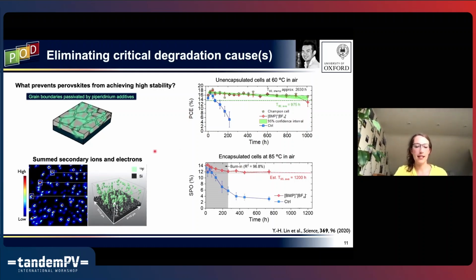So that was really neat to see. And then if we look at the SIMS measurement down here, this is tracking the fluorine signal. We don't see that the piperidinium salt is really well mixed into the perovskite. We see these regions for the fluorine signal, which makes us think that the piperidinium additive is actually just on the grain boundaries and not mixing in homogeneously into the film.